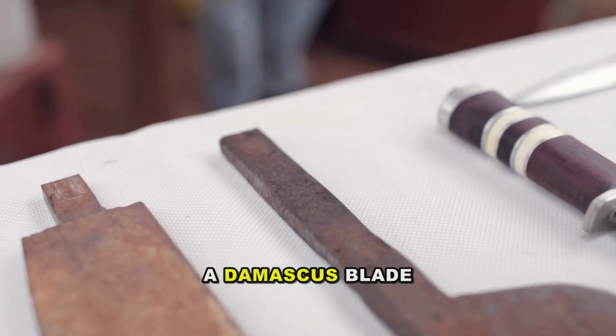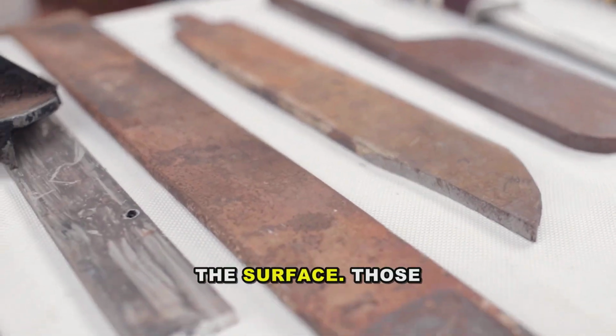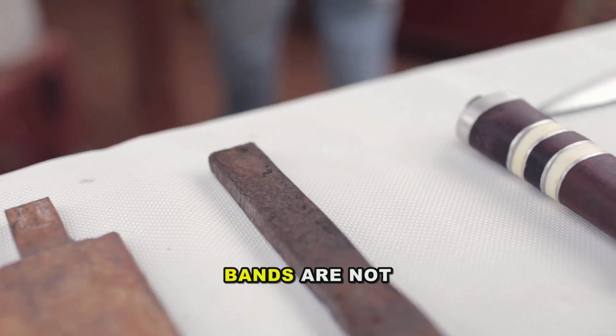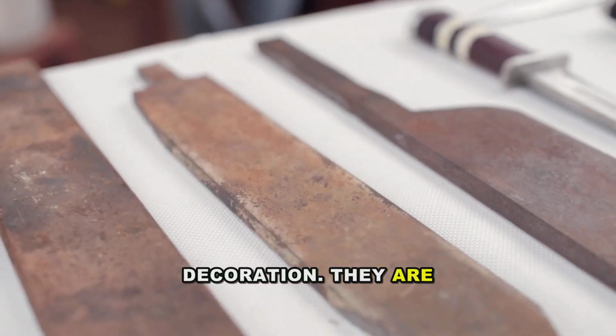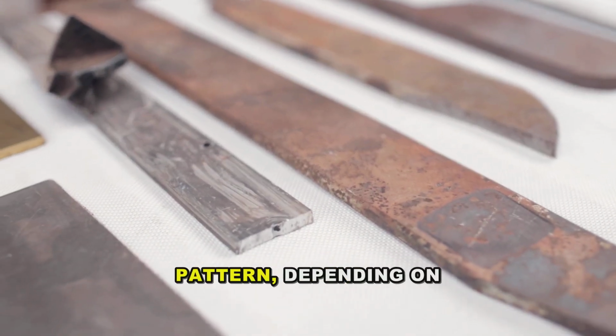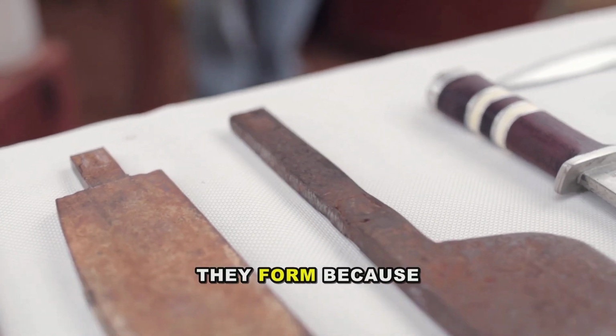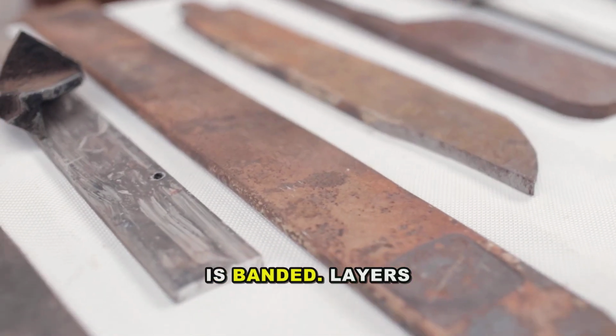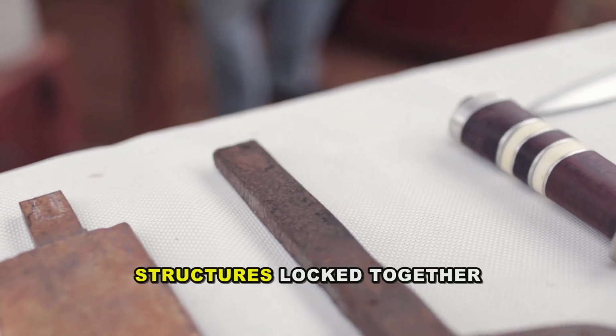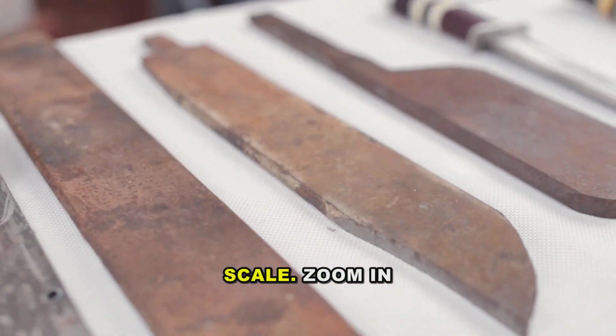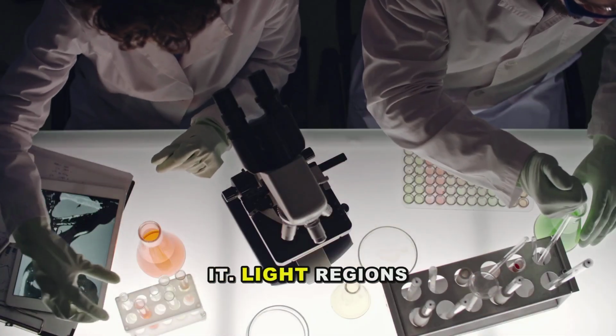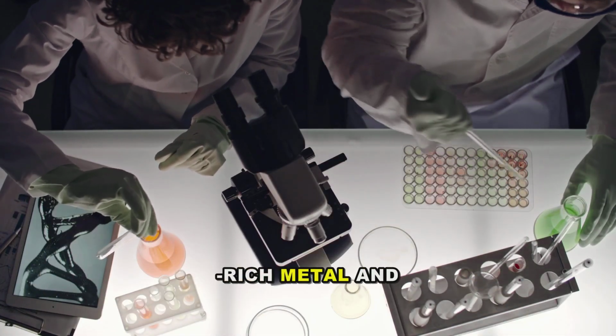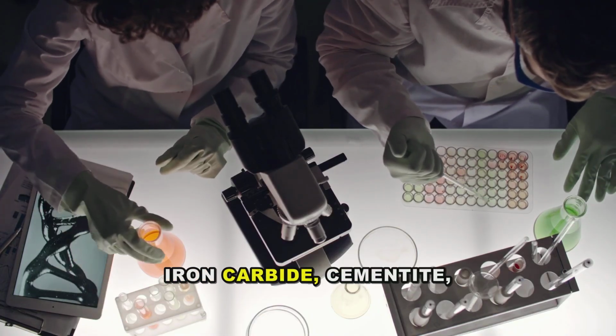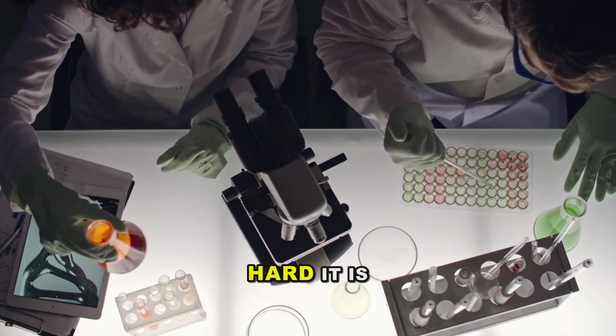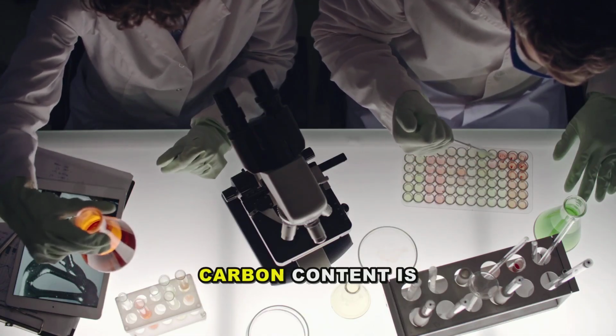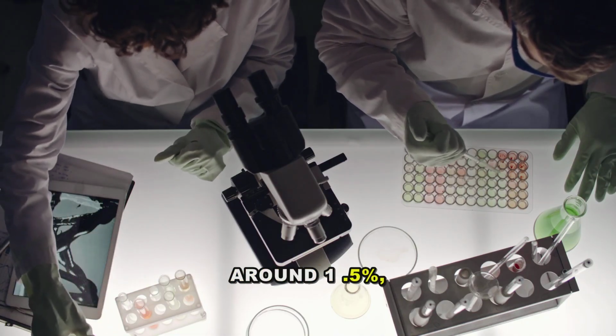Here is what makes a Damascus blade different. Start with the surface. Those flowing, ladder-like bands are not decoration. They are called Muhammad's ladder or the rose pattern, depending on the smith. And they form because the steel itself is banded. Layers of different crystal structures locked together at a microscopic scale. Zoom in and you see it. Light regions of soft, iron-rich metal and dark lines of iron carbide, cementite, a compound so hard it is almost ceramic. The carbon content is around 1.5%, sometimes higher.